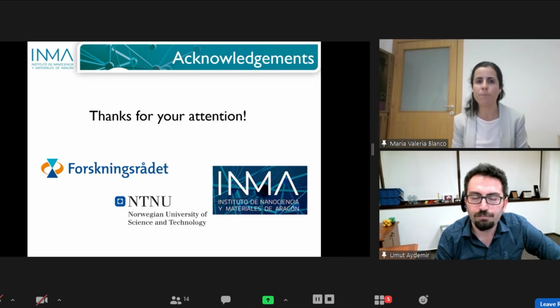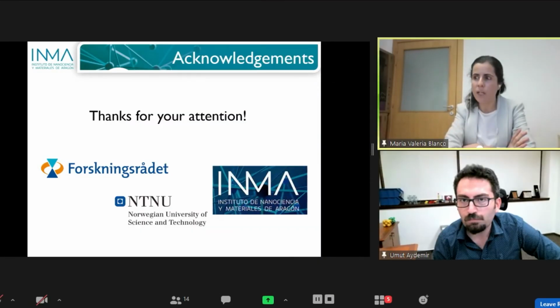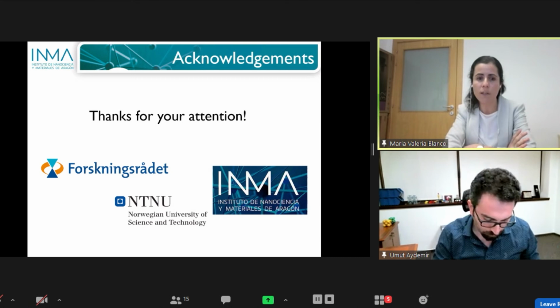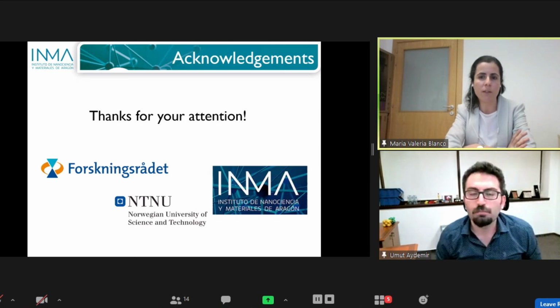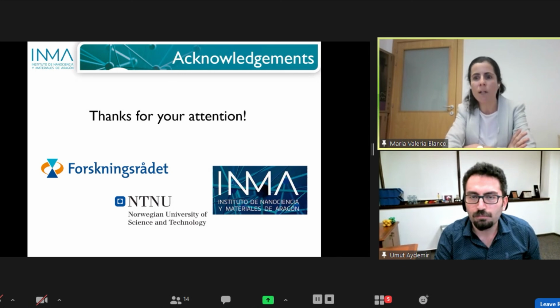It's interesting. And maybe a last question, if it's possible. You talked about uncoated silicon anodes. So what does it mean? Did you use carbon conductive powder or didn't use it at all? Yes, we used some cheap and eco-friendly supplies, which is why we use sucrose as a carbon precursor to make the coating. We have 13% of carbon in the total composite. But the coating is something that even graphite anodes have. So it's normal for any anode material to have some coating layer.